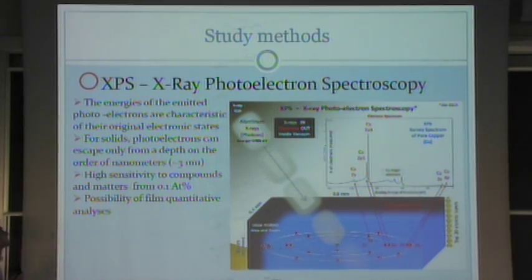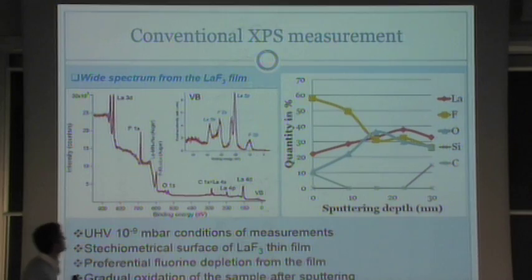we've used X-ray photoelectron spectroscopy. In a few words, if you have a source of light and illuminate the substrate with it, you can excite electrons, and by looking at the electron spectra, you analyze the energy of electrons with a special analyzer, which gives you a sort of fingerprint of your material. And as you can see here, it's a fingerprint of lanthanum fluoride, where the binding energy of the peaks, and actually the intensity of the peaks presented here, is also important.